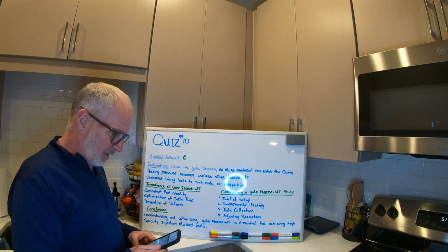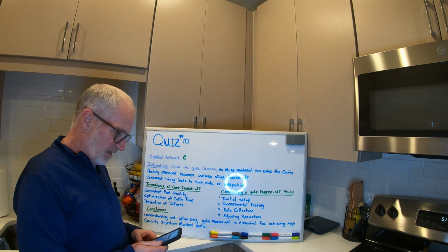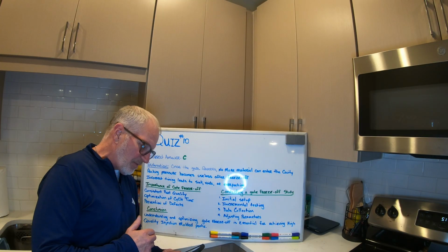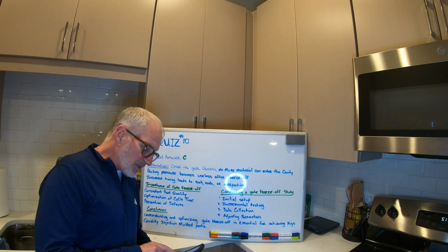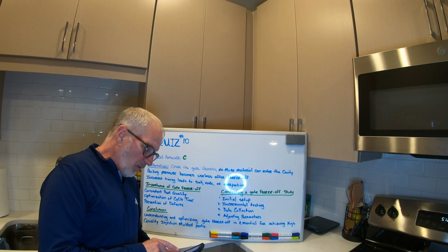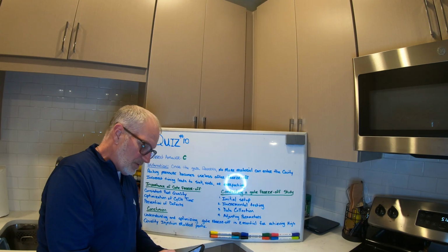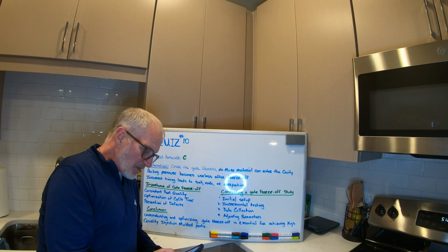Now, if you look at conducting a gate freeze-off study, like I said, initialize setup. I wrote these down from what I've done before. Load your mold and set the machine to a long pack and hold time. Then you're going to do the incremental testing. You're going to gradually decrease the hold time while monitoring the weight of the produced part. This will help identify the point at which additional hold time no longer increases part weight, indicating that the